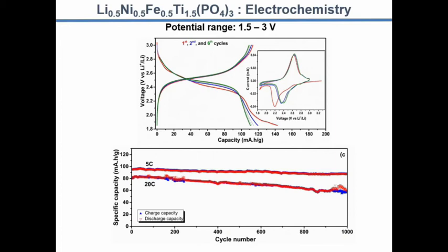So for these two phosphates, we have the mechanism of insertion, no conversion and no alloying. This is the mechanism of insertion. Lithium is introduced to the structure. We have weak bonding, and during charge, we extract lithium very easily, and we got reversible charge and discharge.